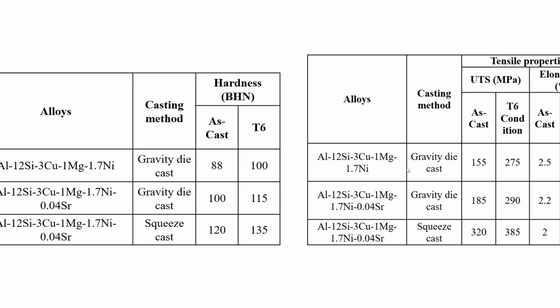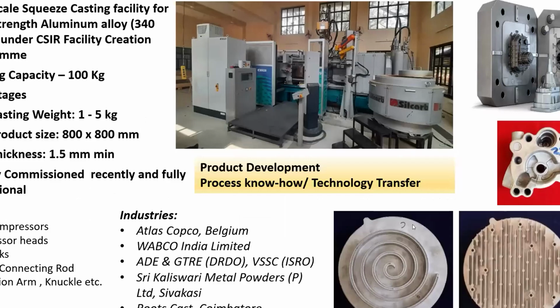For example, you take this aluminum silicon-based alloy, you do gravity casting at the heat-treated condition, the ultimate tensile strength is almost 275. And you can see this squeeze cast heat-treated is 385. So more than 100 megapascal increase, the yield strength in the squeeze cast is higher. Even the percentage elongation is slightly affected because of the squeeze cast grain. However, the strength properties are very much improved, and the component produced is also highly integrated.